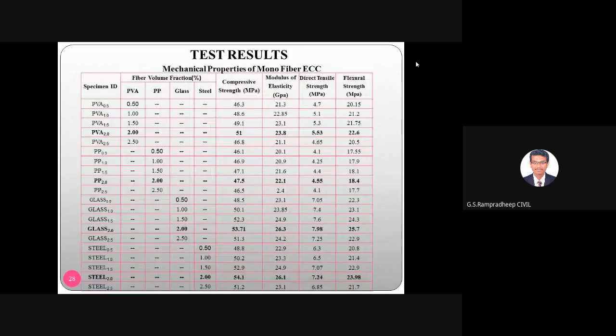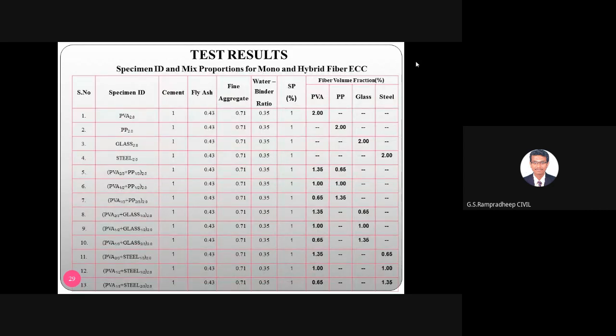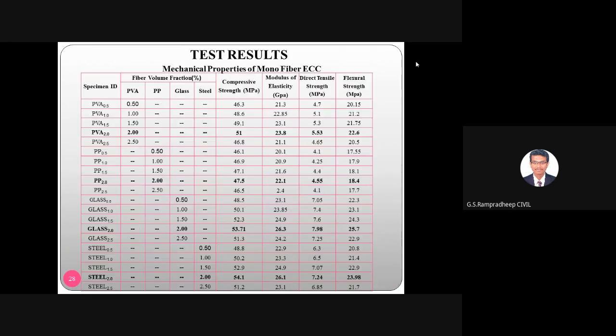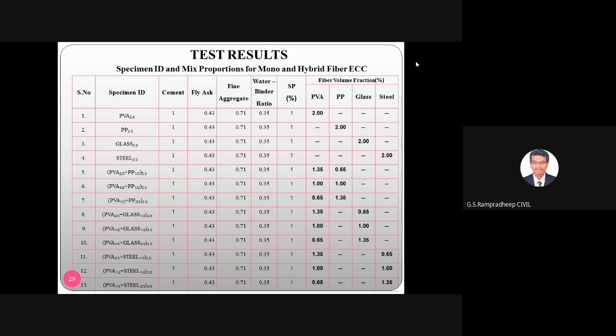So the earlier slide is for a monofiber, and this is for monofiber and hybrid fiber. What he is doing in rows 1 to 4 is taking only the best mix. From the monofiber, he is varying the volume fraction from 0.5 to 2.5, and for overall observation he is taking the best result, 2% volume fraction. From that, he is going for the hybrid blending analysis. First to fourth is PVA to steel 2%. In the 5th to 13th, he is making the blending. How is he making the blending?